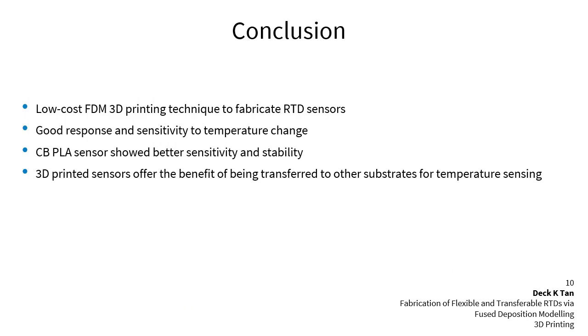that uses low-cost FDM 3D printing to produce flexible RTD sensors, the fabricated flexible RTD sensors showed good stability and temperature response despite the poor resolution, and the conductive materials used, although in the form of polymeric filaments, show excellent conductivity, response, and also sensitivity to the temperature change.